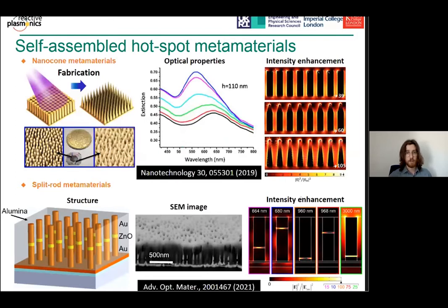So other metamaterials that we fabricated were fabricated using electrodeposition and anodized aluminum oxide, where we deposited nano rods of gold, for example, and then we can change the aspect ratio of these rods. So this is a large-scale fabrication process, which allows us to deposit over wide areas, so we can have a broad area of hot electron enhancement and high field enhancement. And we can shift the optical properties by changing the aspect ratio using argon milling to move from nano rod materials to nano pencil materials and then to nano cones.